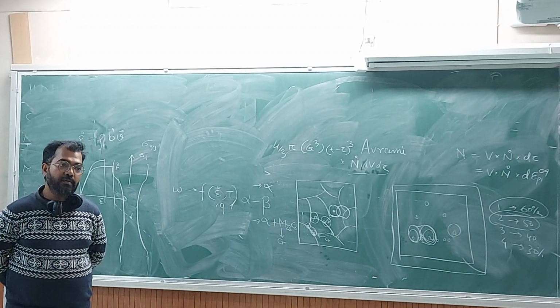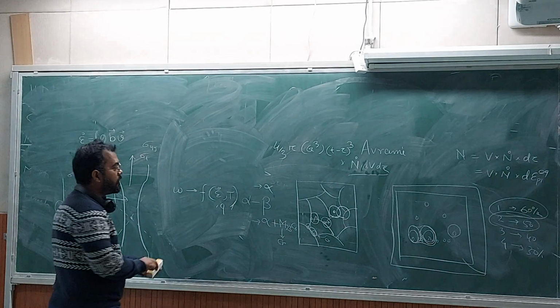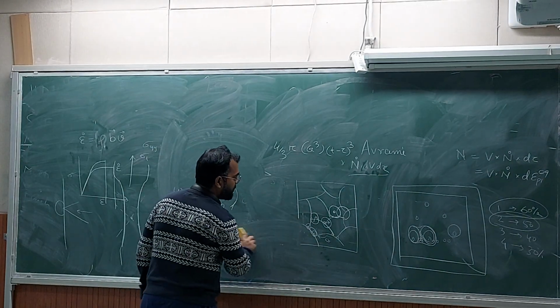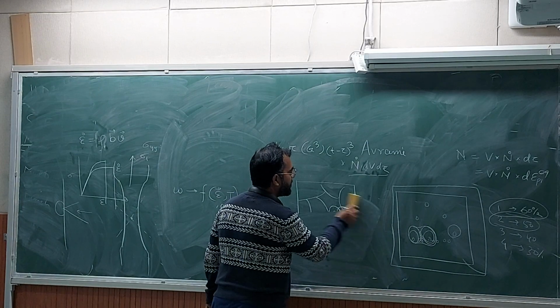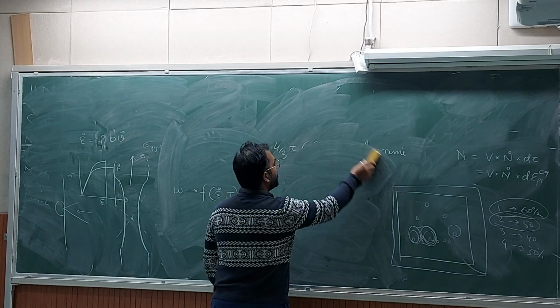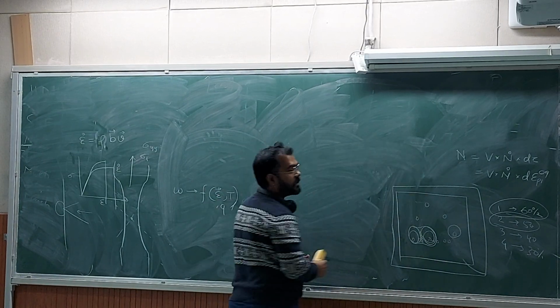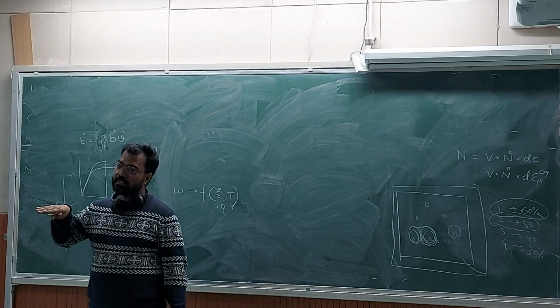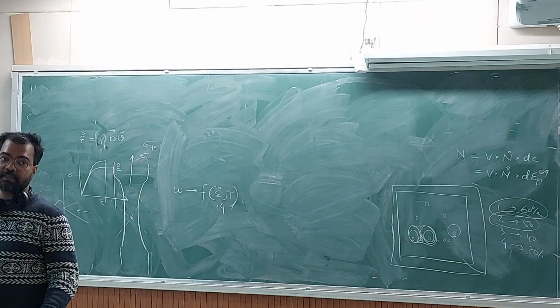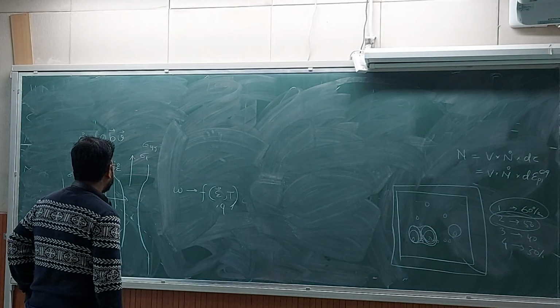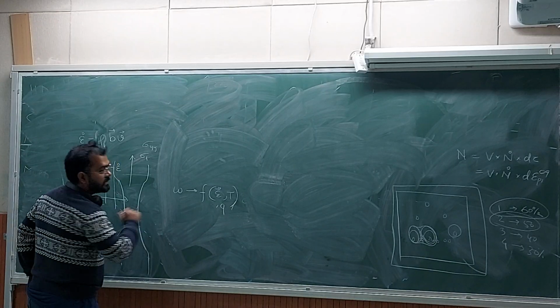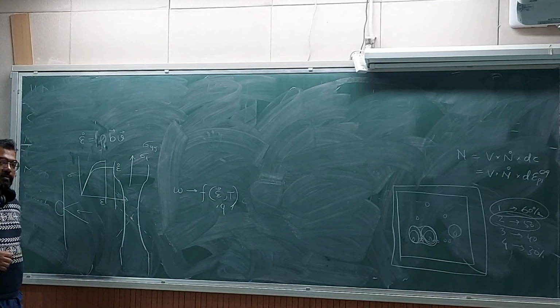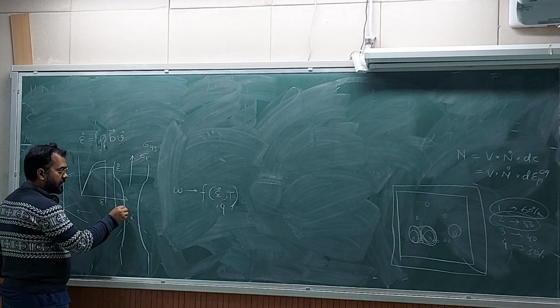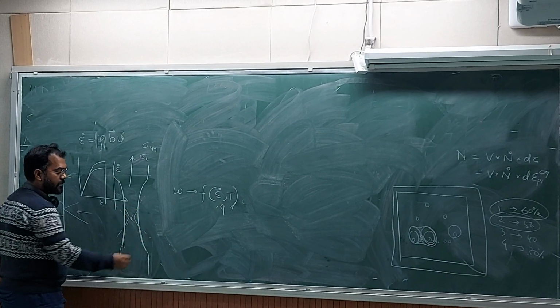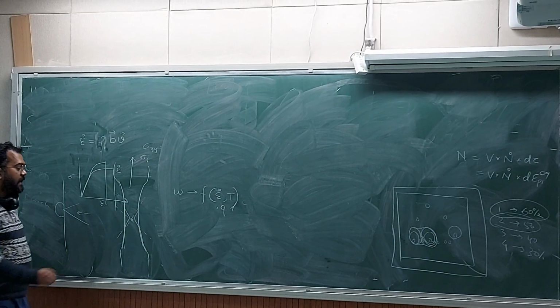Okay. So in order to find out how the damage changes, we have discussed that experimentally you can do resistivity measurement. You can cut a tensile sample at different sections and then look at it under SEM and find out how much damage has happened. Then you need to change the constraint and see how the damage changes. One tensile sample, I deform it until necking, then I cut it.